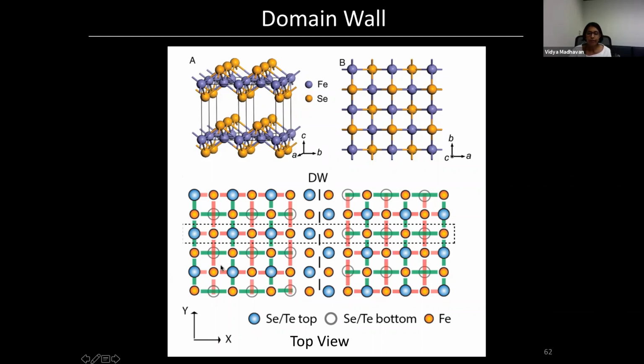So on the left side of the domain wall, you can see these are the top selenium atoms, these in blue, right? And as you go across the domain wall, you can see that there's a shift in the crystal structure, where now you don't have the top selenium anymore. You have it phase shifted by half a unit cell.